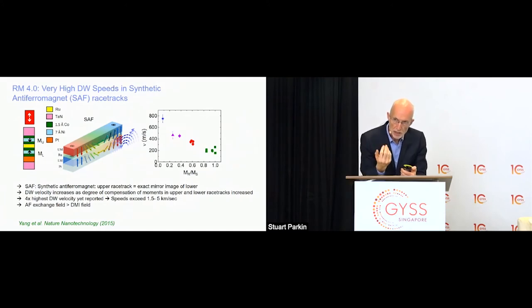But in the end, you have a racetrack where there is no net magnetization anywhere in the racetrack, therefore no dipole fields. And nevertheless, when we did this, we discovered that current pulses passed across this domain wall would move it five times more efficiently than in an identical structure where the ruthenium thickness is changed by 2 angstroms and the coupling is ferromagnetic. So this is shown on the right-hand side when the magnetization in the upper and lower racetracks are exactly antiparallel to one another and of the same magnitude.